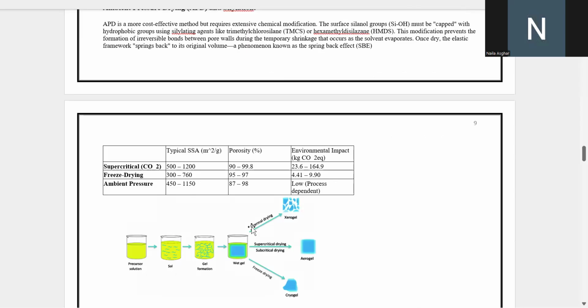And the third is ambient pressure drying, the chemical reinforcement approach. This is the more economical method for mass production. Before drying, the gel's internal surface is chemically modified to make it water repellent. Then the liquid is carefully swapped out for one with very low surface tension, like hexane, and slowly evaporated at normal pressure. While some shrinkage occurs, the pre-strengthening of the network during the aging step helps it withstand the mild capillary forces, resulting in a good though slightly denser aerogel.